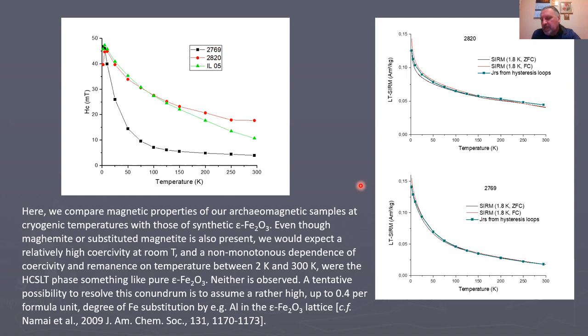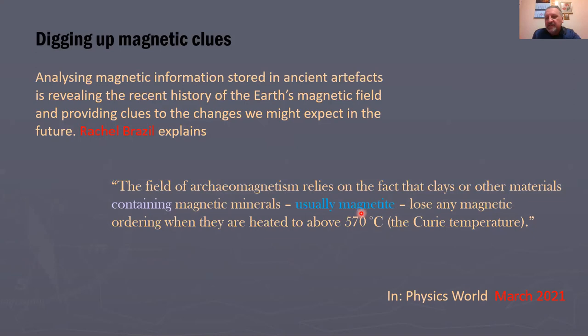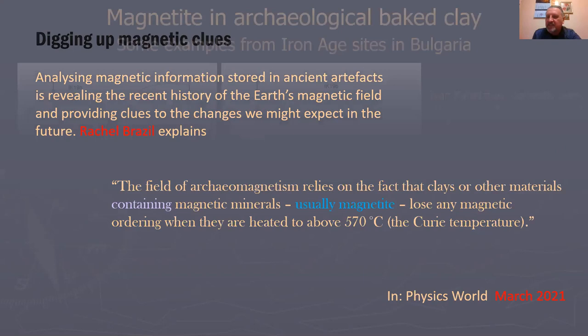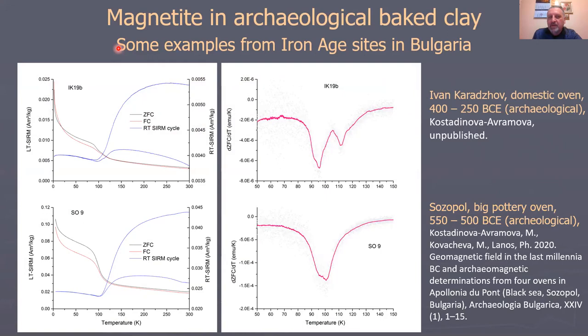Now, much ado for epsilon phase, and we are getting back to magnetite. And just maybe one month ago, I would say magnetite is never observed in archaeological samples, but never say never. Recently, we studied a few samples from Iron Age sites in Bulgaria, and they showed quite a nice Verwey transition, a doubled one even in this case. And an interesting thing about these two samples is that the ZFC curve runs higher than FC, which is obviously an indicator of rather large grain size of magnetite in this particular sample.